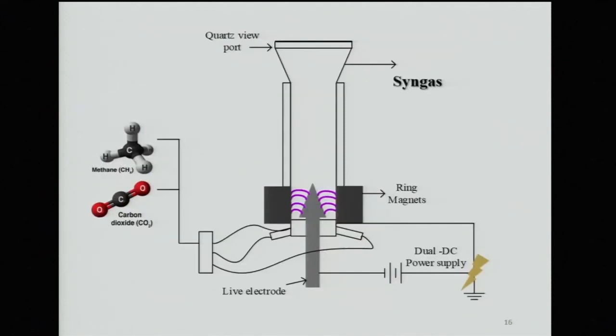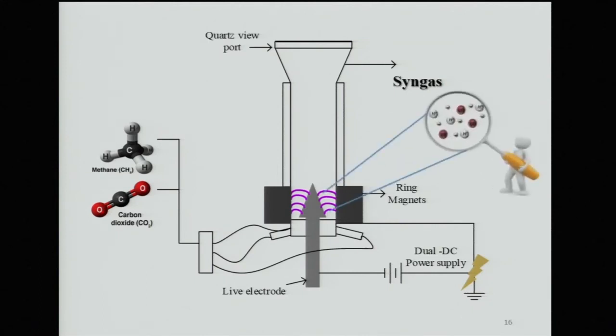In my project, I have developed a plasma reactor configuration called gliding arc, where carbon dioxide and methane are injected through the reactor where an electric field is applied, breaking the molecules. And if you see in the schematic these pink lines, this is where the plasma is happening. So we can see this pool of very active species happening there. So they are going to recombine, and they are going to produce syngas.